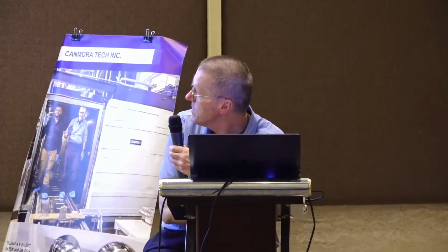Okay, good. So now we go to the question: okay, but if that plasma comes out, what's happening to the surface, right? So each laser gets its own reactor chamber. Around the beam that goes on the surface, it starts the melt pool. So the thing that happens when you look here is the gas comes out. So we create this zone 1. Zone 1 is actually the melt pool recoil pressure. It's coming out of the surface, right? So there's a gas jet.